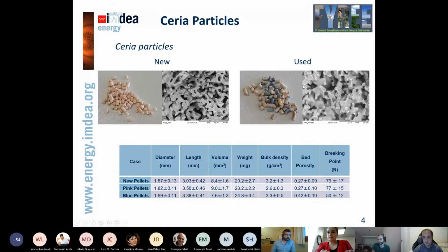We're talking about hours and not cycles, basically because we are trying not to cycle but to do the process in a single step. If we just check the characterization of those particles, the most noticeable difference in the used particles is that there are some that are blue, and as far as we know, this is due to the presence of hydrogen during the reduction stage. So it's something again that we can expect since we are working in a single step. So that's why we divided here between these two types of particles.